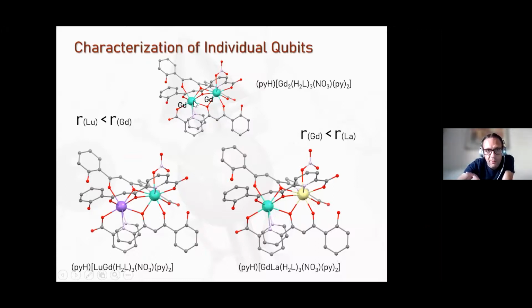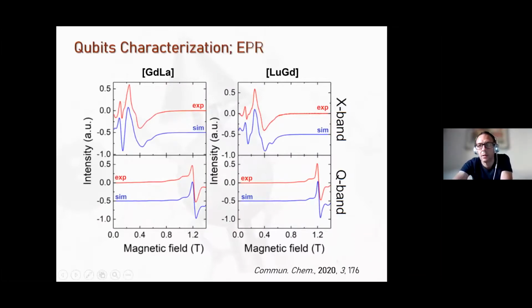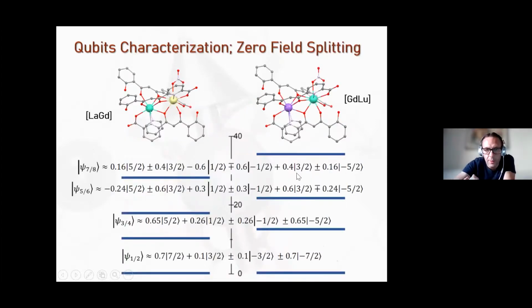And conversely, if we want to study the gadolinium in the position for the small metal, we made the compound with lanthanum, which locates gadolinium in this other position. Therefore, by putting a diamagnetic metal in the other position, we can study the characteristics of gadolinium in each of these two positions. So we did that, and we studied it. Then we did the characterization by different techniques, for example, Q and X-band EPR for both gadolinium monomers. That allowed us to identify differences in the zero field splitting of those ions between both positions.